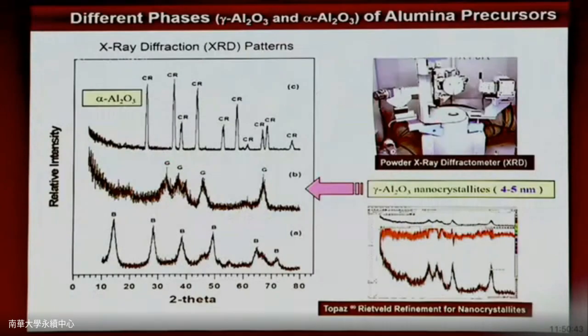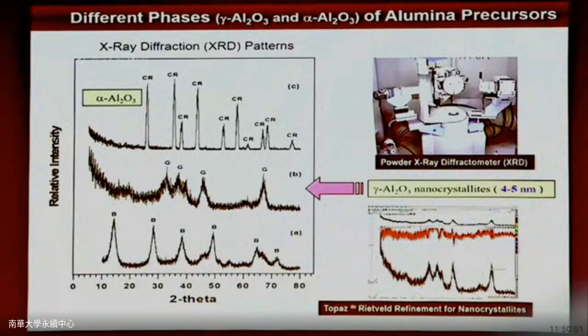So we use the X-ray diffraction techniques, and then we find out it's the nature of the system that most environmental chemists only look at the chemical formula, which is not enough. You should look at mineralogies. For example, aluminum oxide, same Al2O3, actually is a different kind of crystal structure. You cannot differentiate by chemical analysis because it's only aluminum and oxygen. But the mineralogies help you to tell different types of alumina, alpha alumina, gamma alumina, for example.